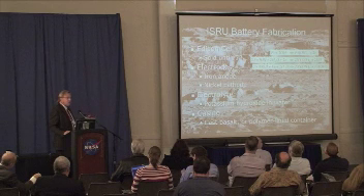There's iron on one side, nickel on the other, and potassium hydroxide is the electrolyte in between. These are very simple, common materials, and they're available on the moon. The electrolyte, we need to have water for this. Now that we've got water at the poles, this is now a viable solution for making batteries with in-situ resources for our robotic precursor mission before the people land with their habitat and need to plug in. The casing for this can be cast basalt, or it could also be a polymer-lined container that we make out of bricks.